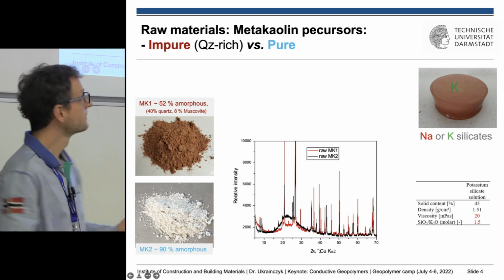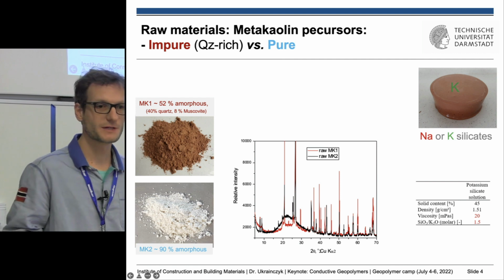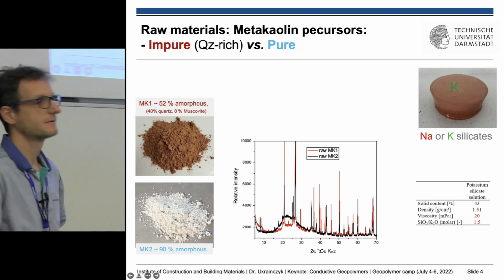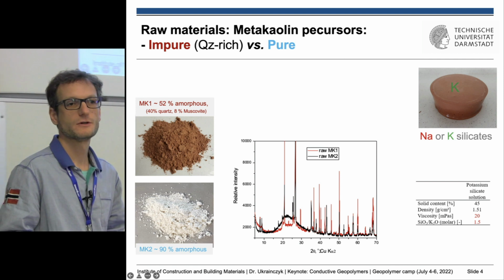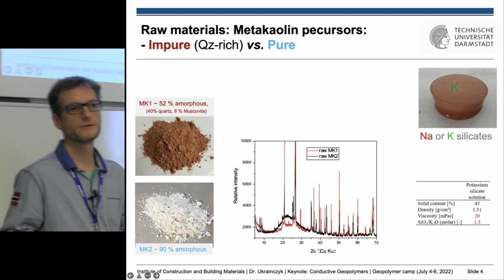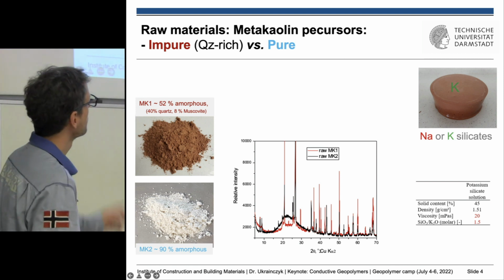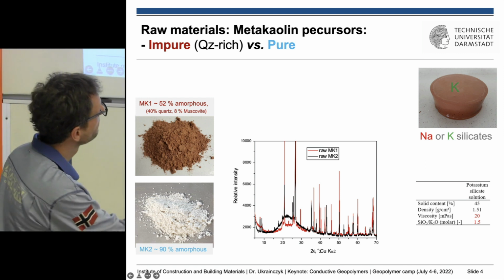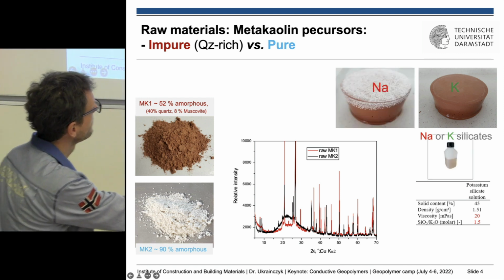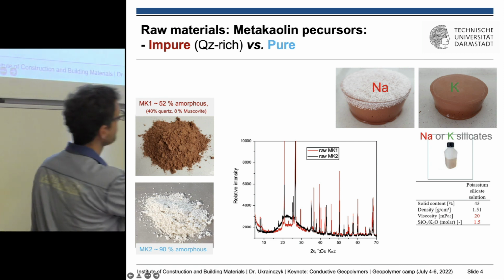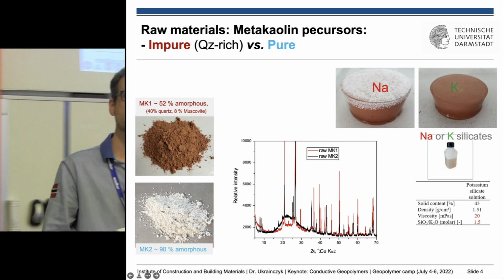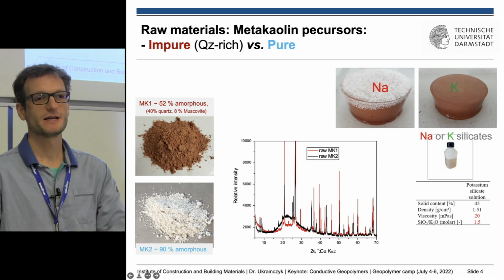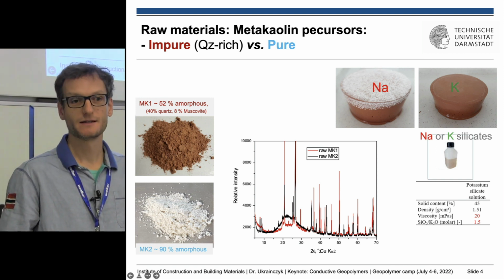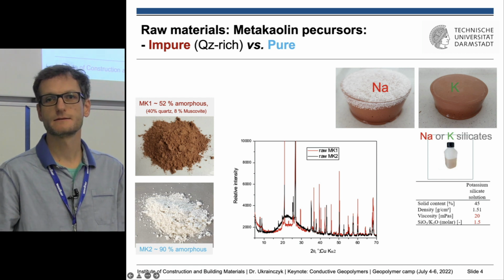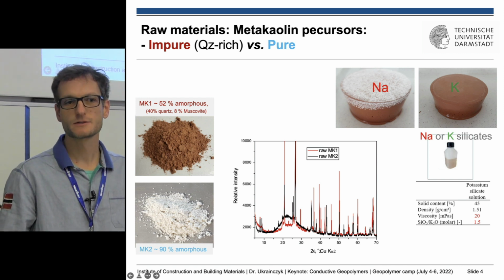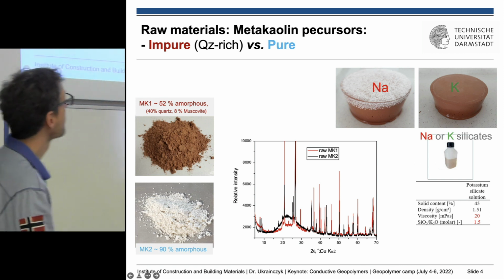And this is very important because then we can use the rules for how to do this mixture, and we know how much silicate we should use, not to use too much silicate because then we have too much leaching. In our case, I think we didn't have any of these kinds of products. We use, of course, potassium silicate because you already saw from Werner's presentation that the viscosity of the potassium silicates is more than an order of magnitude lower, so it's much better for the workability.